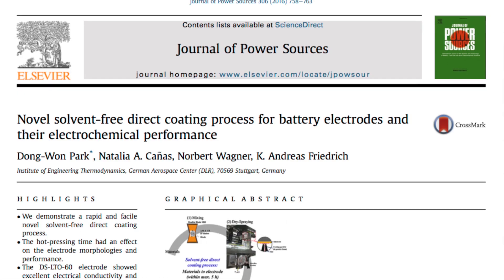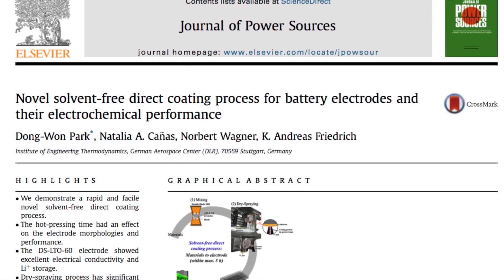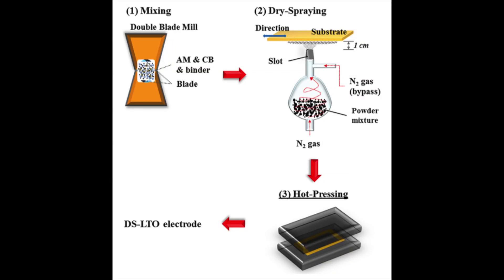In another study by Park et al. at the German Aerospace Center, researchers made lithium titanate or LTO batteries with a dry electrode process. Instead of using an electrostatic application method, as in the previous study, they used a dry spraying method after thoroughly mixing all the materials.